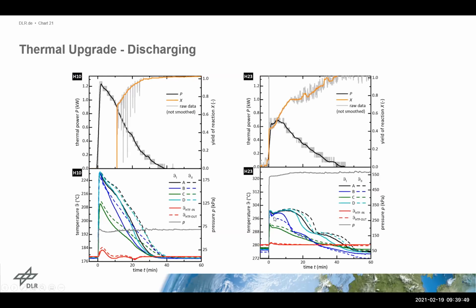And of course, we could also now increase the temperature. We have now 280 degrees Celsius. That's discharging temperature. It's useful temperature for our process at the end. We have a smaller temperature difference again. So it's slightly smaller thermal power, but we have almost full conversion.